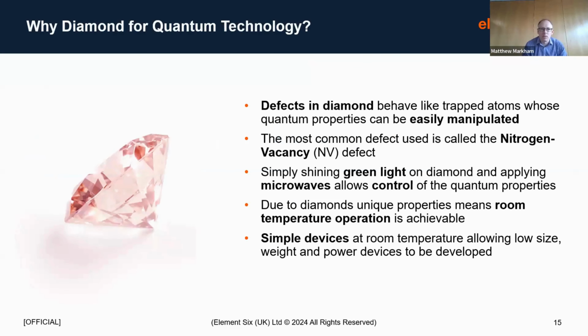So why is diamond an interesting quantum material? It all comes down to specific properties around defects in the diamond material, and these are defects that you actually want. These defects behave effectively like trapped atoms inside the diamond crystal lattice. What's really key about these defects is you're able to manipulate their quantum properties. The specific quantum property we're talking about here is the electronic spin associated with these defects, the most common one being the negatively charged nitrogen vacancy defect.